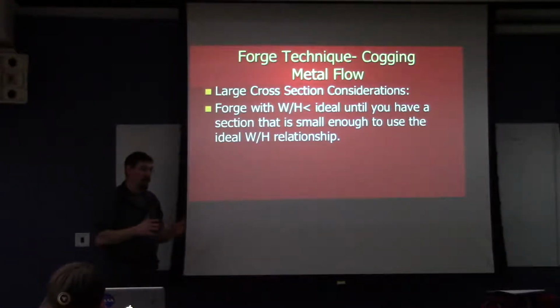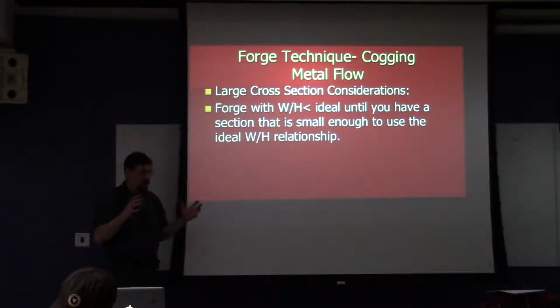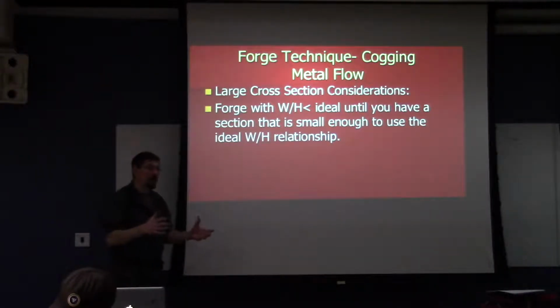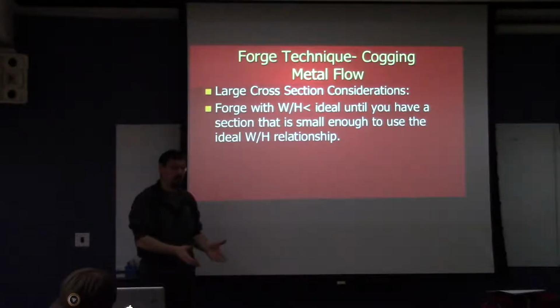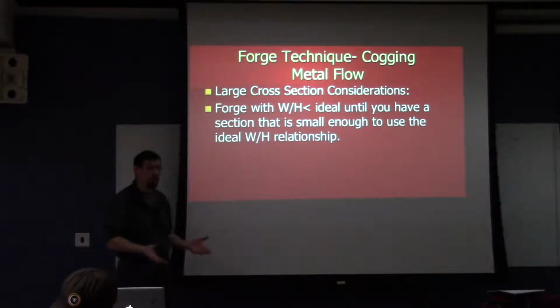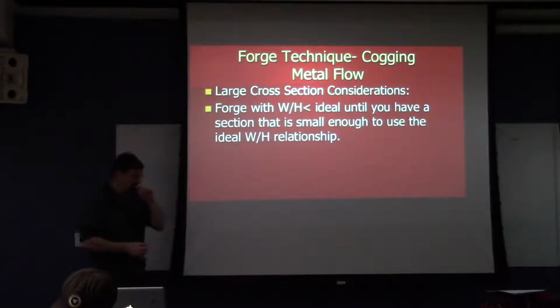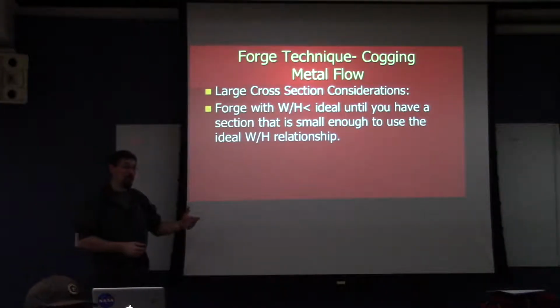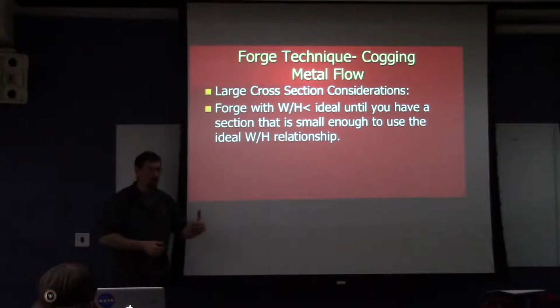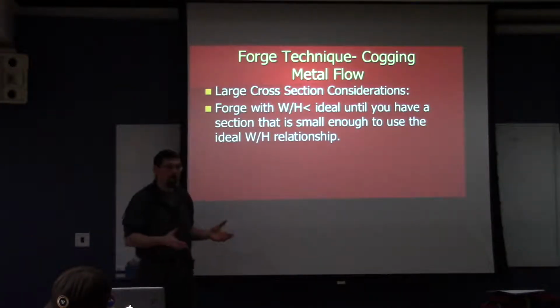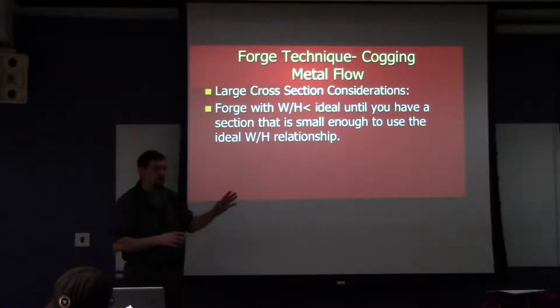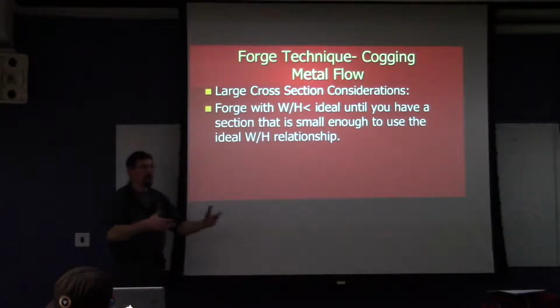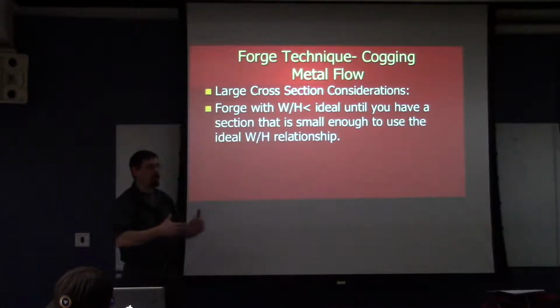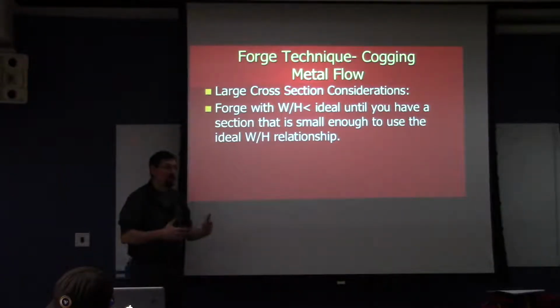Again, there's a tendency for operators to want to get as much work done as they possibly can in the shortest period of time. That's just how they're efficient with their time and energy. So what they'll often do is keep forging until the piece is too cold for them to really work it anymore. Then they'll put it back, let it reheat, and bring it out. We call those multiple heats. Every time we go in and out of a furnace like that, that's a heat. So they'll have multiple heats.